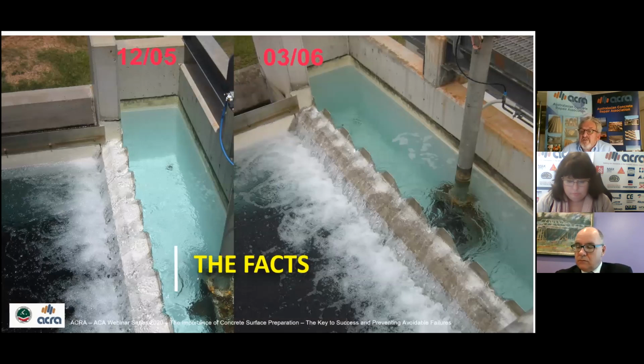There's a case history over there on the screen. You can see there 3 weeks after application. This is on a water treatment plant filter. 3 weeks after application, the high build coating was washed off the concrete surface. And findings out of that was there was an inadequate surface profile on the concrete to provide an adequate anchor pattern. It was prepared by low pressure water jetting. And I guess too, the anchor pattern that we're looking at here is not so much pull-off in tension, but we had water running over it. So the loading on that coating was a shear loading going across. The anchor profile was obviously inadequate to do that.